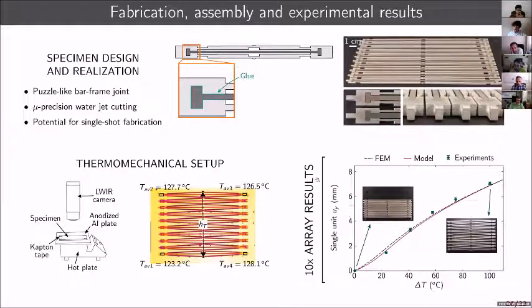And here you see a plot. We did these experiments on a 10 unit array, but we divided the response by 10 and compared it to the expansion of a single unit. Here you see the expansion of a single unit as a function of delta t, for numerics, the dashed red curve the model, and the experiments the green dots. You can see that the experiments match pretty well, and we also like the fact that it tracks this change of inflection of the curve.